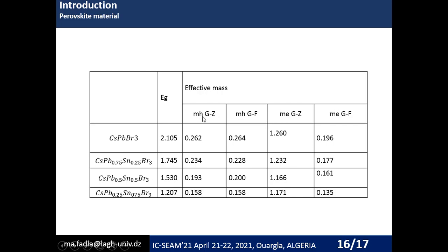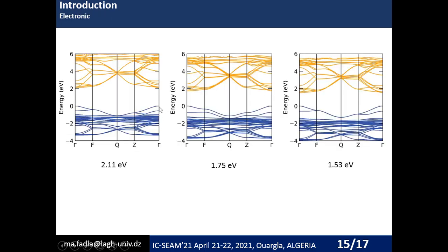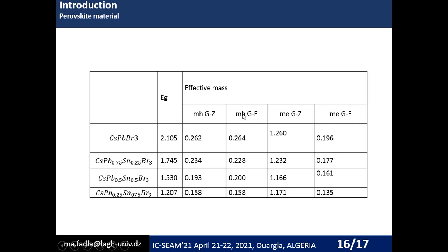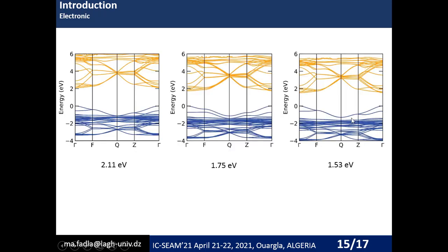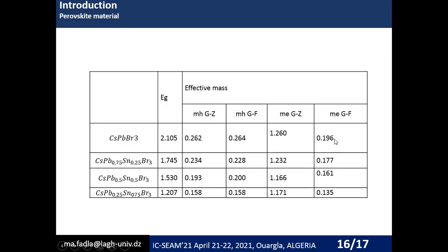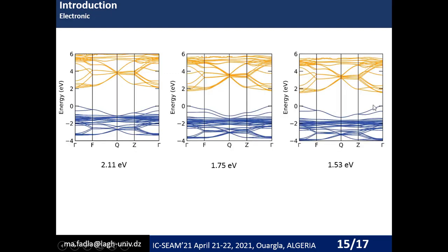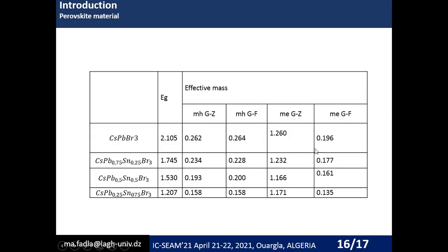Here I calculate the effective mass in different directions, in this direction gamma to Z and gamma to F. As you can see, for the hole we have an isotropic character of the effective mass, but for the electron effective mass we have high anisotropy. In the gamma to F direction the effective mass is equal to 0.2, and for the Z direction the effective mass is much higher, 1 point something.